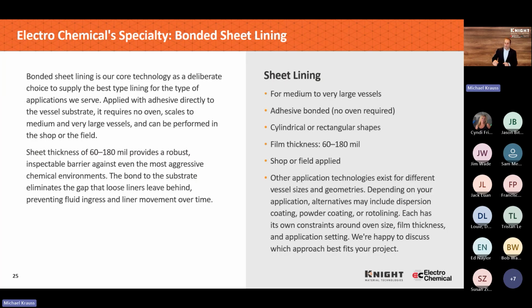We have a contract with a customer right now to do field installation of a couple fluoropolymer lined vessels, and these tanks are being built in the field, will be 30 feet diameter, some odd feet tall, and we'll have a crew go out there and do the lining in the field. So where a lot of equipment you're limited to how big can you get into an oven or rotational lining equipment to be able to physically make it, how big can you ship it. In our case, once it's too big to ship, we can actually go on the field on site and apply the lining inside.